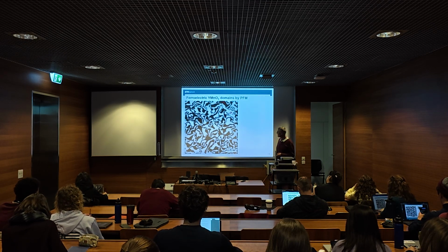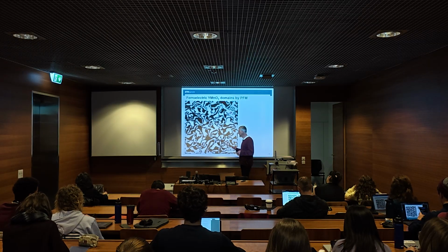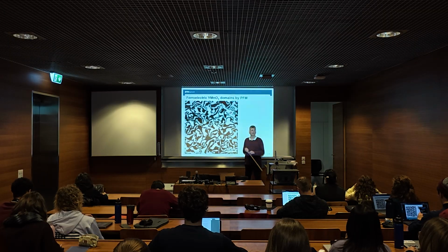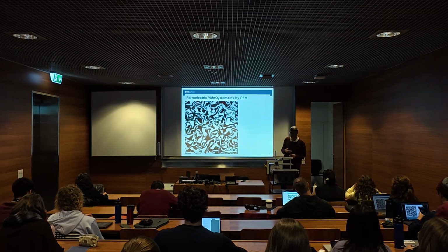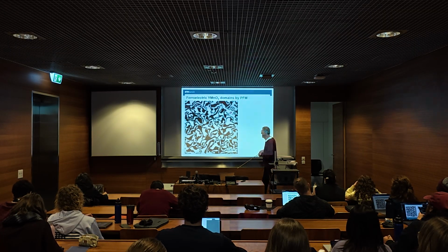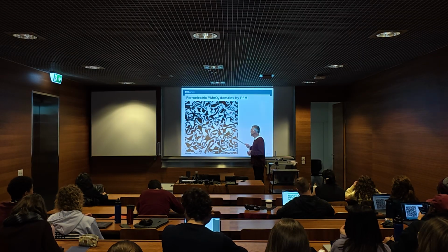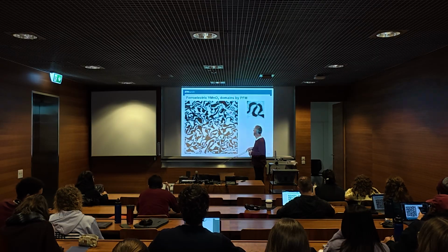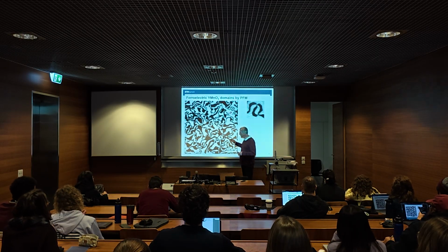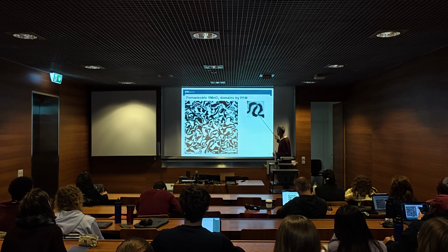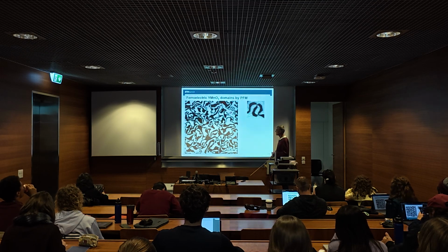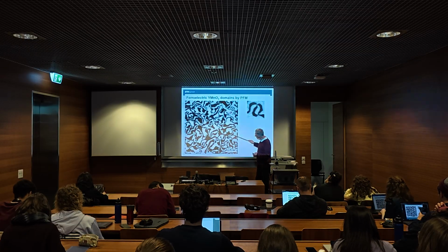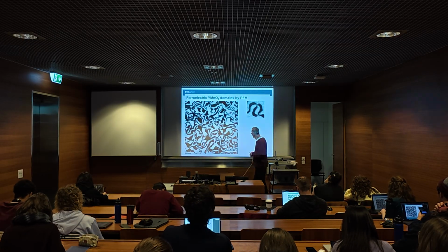What is a bit unusual about this pattern, and this is a little sidetrack why I'm showing it: if you look at that, you would say this is not like cow patches, like curly domains distributed in some form, but something is odd here. Although at first you may not easily see what it is. If you stare at this long enough, in the end you will find you always have meeting points of 6 domains. Bright, dark, bright, dark, bright, dark. So always 6 of these meet in one point. Wherever you go, there's no exception.